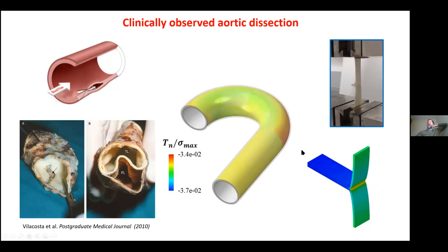The problem with the state of research to date in understanding aortic dissection is that the experiments people do are typically peel tests. This is a peel test. You take a piece of aorta and make a small notch, catch one part of the notch and pull upwards, catch another part and pull downwards, and peel it apart, like I'm showing in this finite element simulation. We're basically opening up a crack like this. This is what we call a mode one crack, because we're pulling the crack surfaces apart. It's what we call a normal opening.